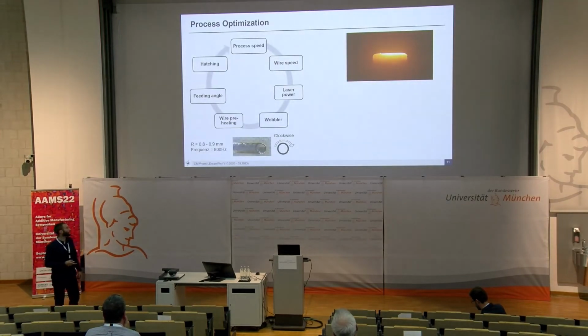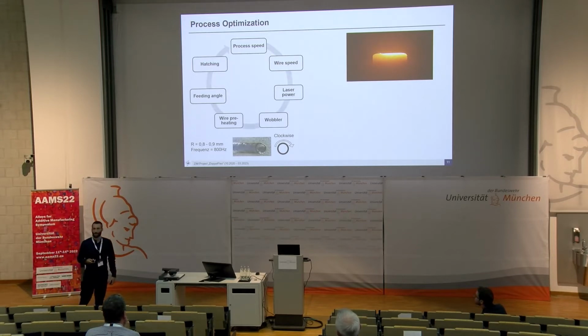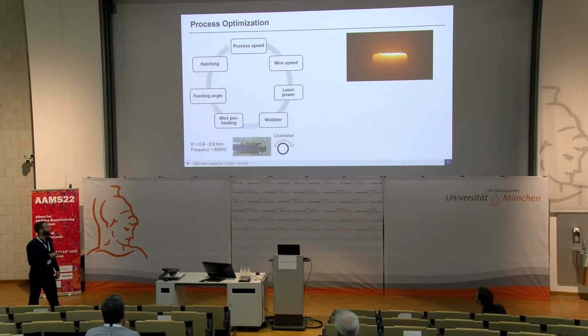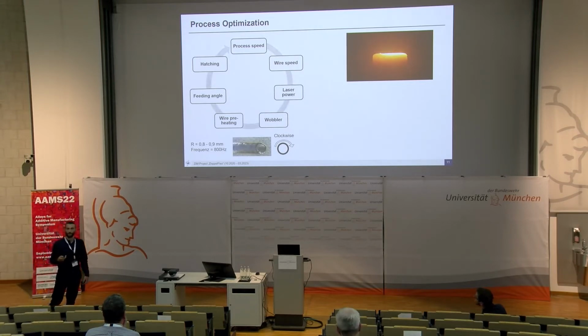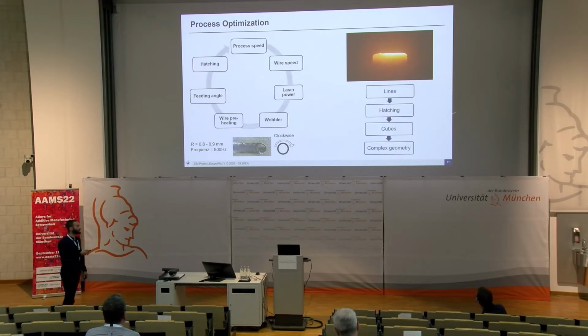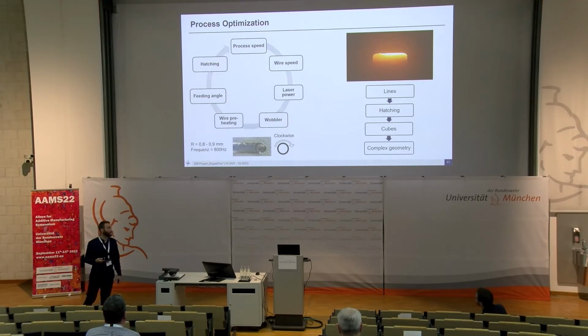So let's talk about the process optimization. A lot of people think that DED processes are a lot easier to control than powder bed fusion processes, for example. It is not like that, I can say. Here are the most interesting parameters. What is interesting, we have a wobbler, so we don't have to defocus our laser to get a bigger welding point. We can just wobble it around and so generate a much higher heating force and a big surface that we melt. We have the standard procedure. We first printed lines, then hatchings, then cubes, and then more complex geometries.